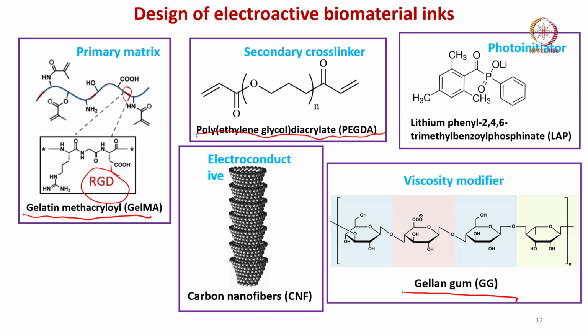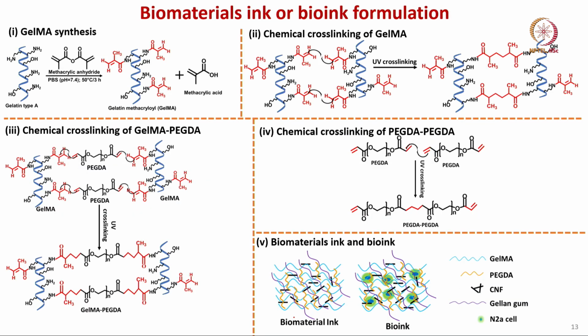Now, to introduce electroactivity, we need an electroactive filler, and as the electroactive filler we have used carbon nanofibers. This is the overall GELMA synthesis process. You start with gelatin type A, and then you use methacrylic anhydride in PBS, phosphate buffered saline, at pH 7.4, 50 degree Celsius, for a 3-hour treatment. You essentially expect the transformation of gelatin type A to gelatin methacryloyl by addition of these functional groups, as I am circling, and the byproduct or residue would be methacrylic acid.